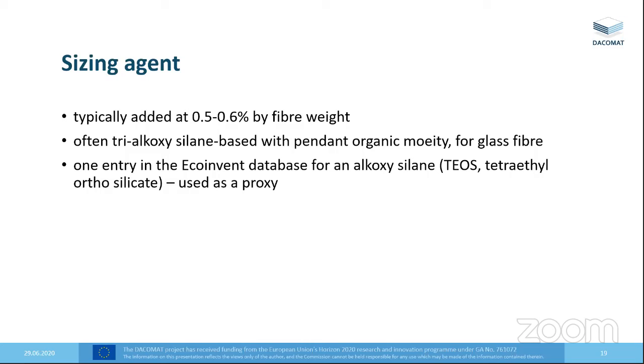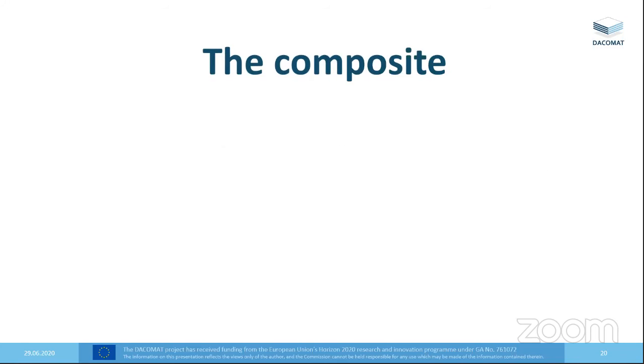So again, as a first go, we look into the Eco-Invent database and we see if there is something that represents the sizing agent. And actually there's something that's quite close to what these agents are, which again, as usual, turn out to be great trade secrets. So we have to use something that we consider to be a reasonable proxy. In this case, it's something called TEOS, which is tetraethyl orthosilicate. So we can use that as a proxy. So then we create a composite, which is a virtual composite. It's a composite that is in our model, it's in our spreadsheet model. And we can do this before they start making the composite.